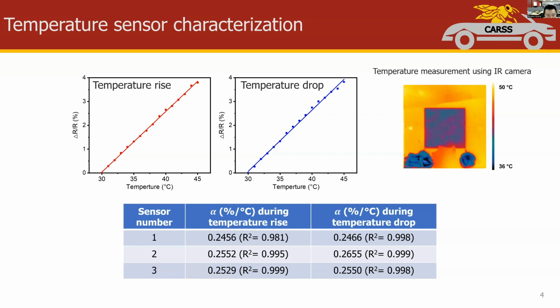Since the least significant voltage level in our current IPG's ADC is about 0.37 microvolt, our temperature sensor can measure at least 0.04 Celsius temperature change, which is sufficient for our applications.